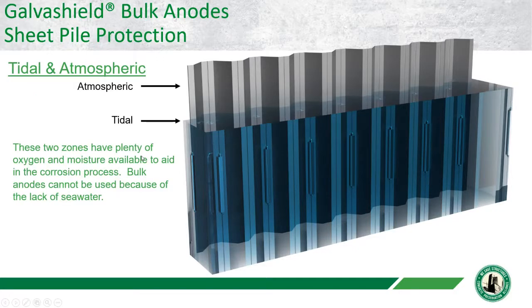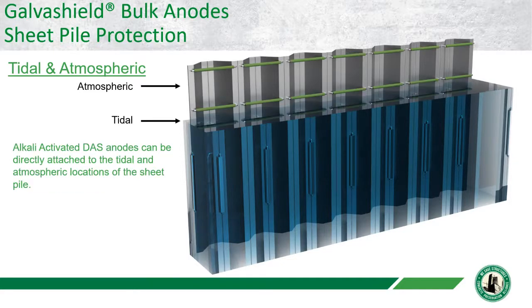So what do we do with this atmosphere for this tidal zone? So as mentioned before, these zones have a lot of moisture, there's a lot of splashing, a lot of availability of oxygen. So the areas here are very, very aggressive. This makes it very difficult. And one of the options that are available is similar to what we did on the concrete piles. What you can do is come in and attach activated anodes within this section.